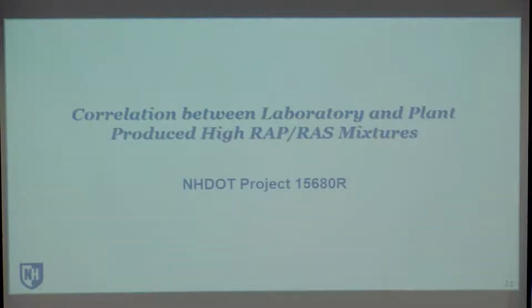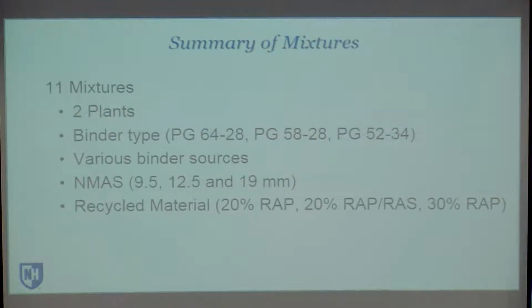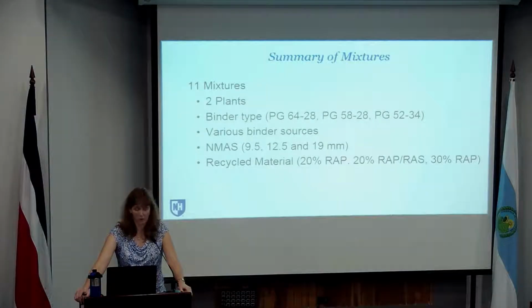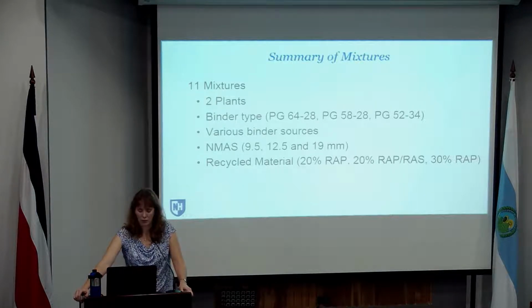Okay, starting into some of the results from the first DOT test, looking at that correlation between those laboratory and plant-produced mixtures. Okay, this study incorporated 11 different mixtures, looking at production that was happening at 2 different plants, recognizing that different plants will operate differently. Looking at various binder types, so we've got a range of the most common PG grade binders that are used in New Hampshire. Also looked at the impact of binder source, recognizing that if we're looking at aging and if we're looking at what's happening in the lab versus what's in the plant, the source of the binder could have a significant difference because of the differences in chemistry.